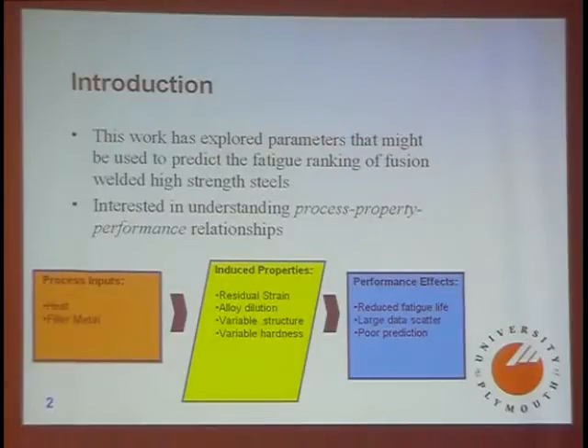So what have I done? Well, we've had a look at parameters that might be used to predict the fatigue ranking of fusion welded high-strength steels. The background of this work was that Corus, the steel maker in the UK, now part of Tata Steel, had done some work on high-strength steels and had found contradictory results for fatigue performance in terms of what they thought the residual stresses did. They were interested in doing some residual stress measurements in these steels, and so I came along and persuaded them to fund a PhD project. And it turned out that the residual stress measurements they made using hole drilling and surface X-ray were not explaining the fatigue data at all.